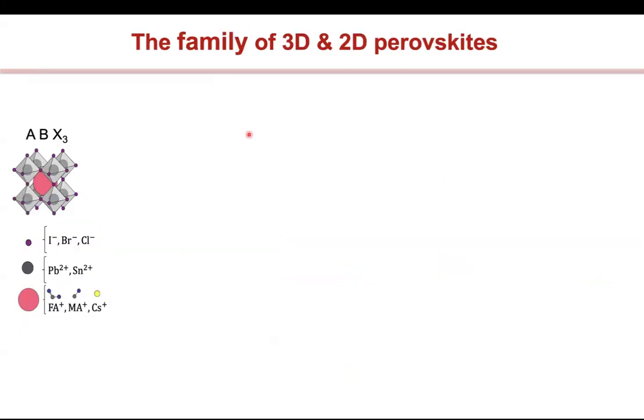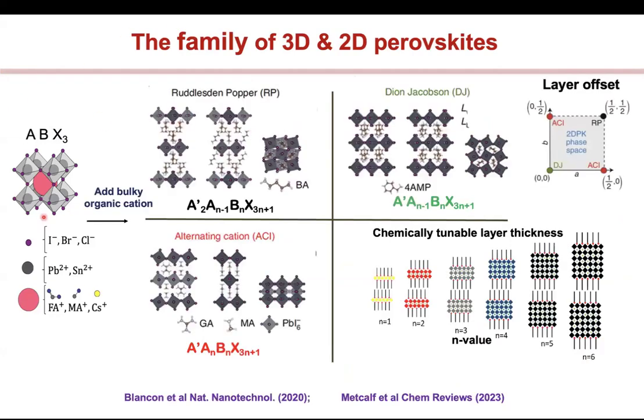So okay, these are the 3D perovskites. Now let's talk a little bit about the 2D perovskites. The 2D perovskites are almost the same as the 3D, but in addition to what I put in the 3D, I also add one more thing, a bulky organic cation. Things like butyl ammonium, or something like 4-AMP, a piperidinium molecule. That molecule cannot really go into the structure, but it likes to settle, and it assembles into a layered structure.